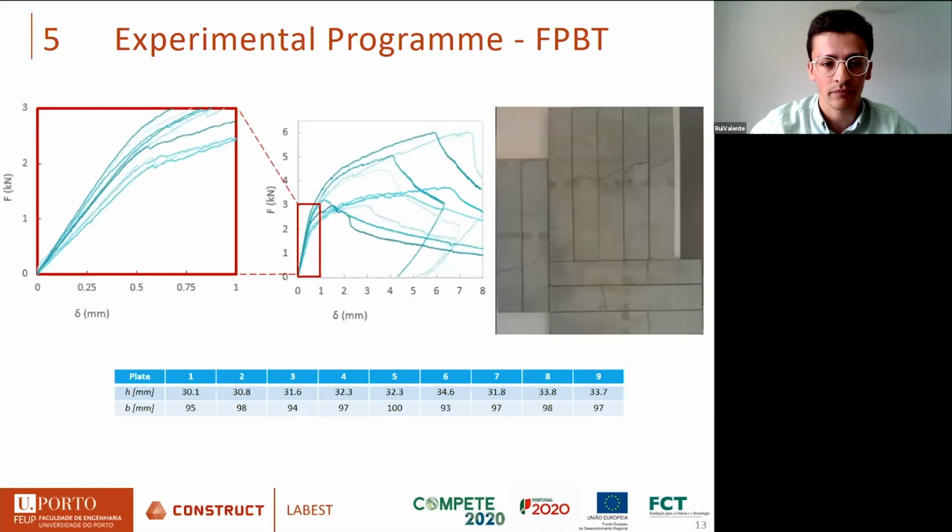And here we have the results of the load-deformation behavior of the plates tested. We have a great variability, which is good to validate our model for different circumstances. Particular attention to the linear elastic phase, where we notice some scatter on the bending stiffness, not only due to the differences in the plate widths, due to the cutting process, but mainly due to the roughness of the top surface of the casting, as I told you before.